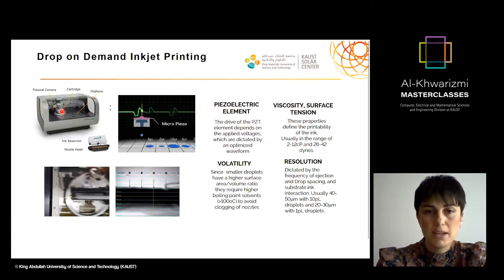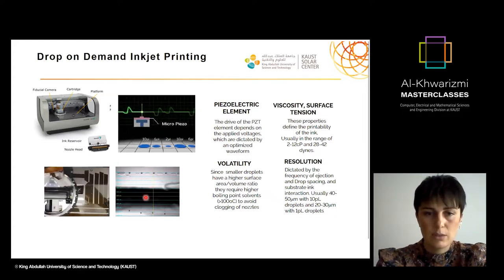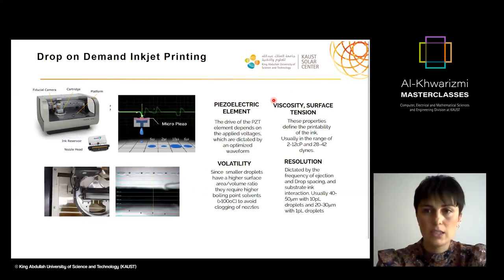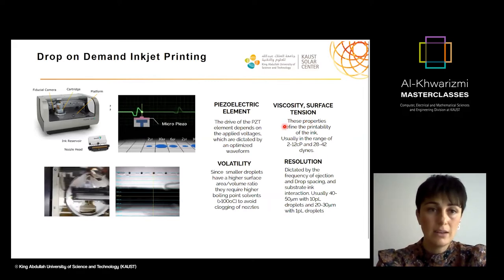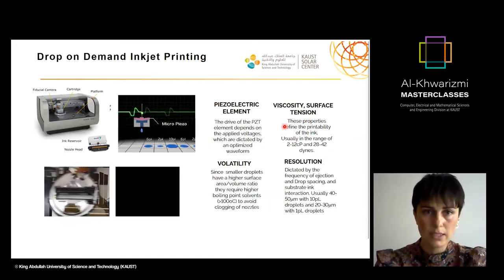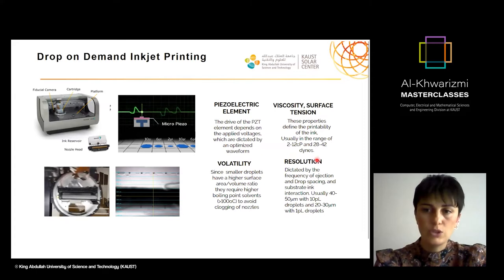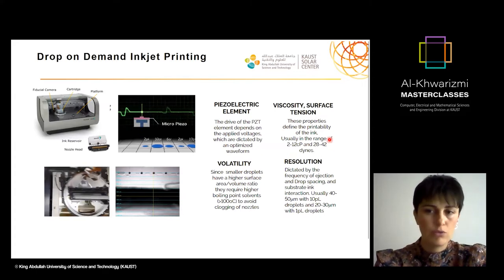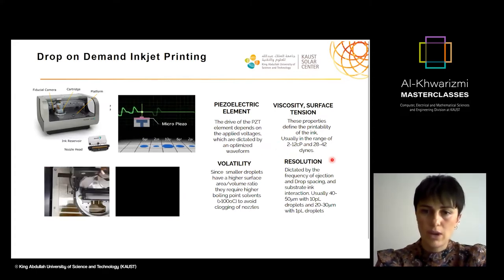The nice bit is you can do several different shapes with this, as you see on the bottom left, Daniel's printing a leaf actually, and you see the proper drops here. So you need to consider viscosity, very importantly, surface tension as well. And you need to have ink properties, not material properties, which should lie between roughly these ranges.